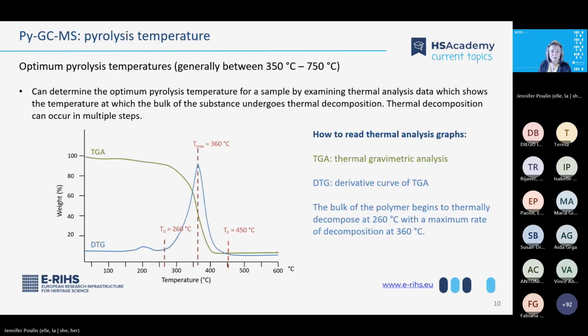How do you choose a pyrolysis temperature? Optimum pyrolysis temperatures are usually between 350 and 750 degrees Celsius, although they can go higher. You can determine the optimum pyrolysis temperature for a sample by examining the thermal analysis data, which shows the temperature at which the bulk of the substance is going to undergo thermal decomposition. And thermal decomposition can occur in multiple steps. In this case, I've drawn one for you.